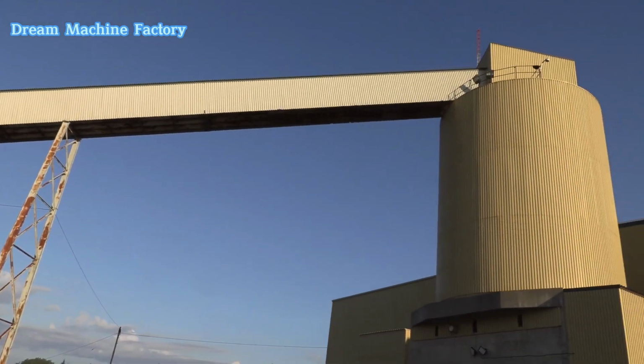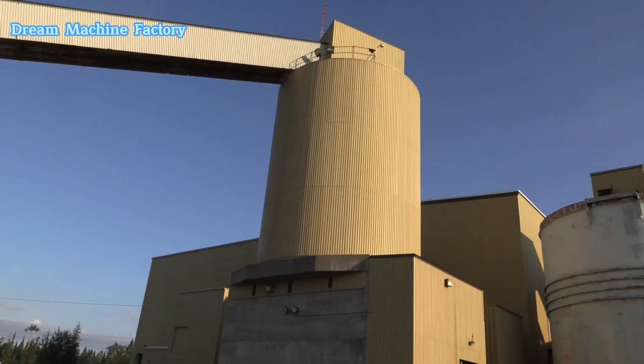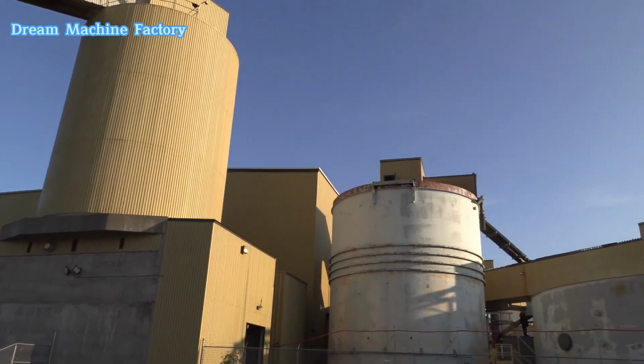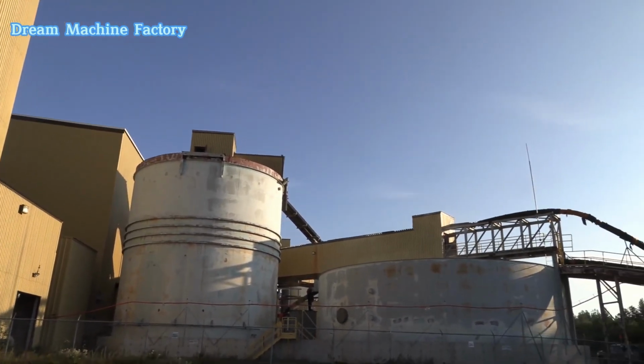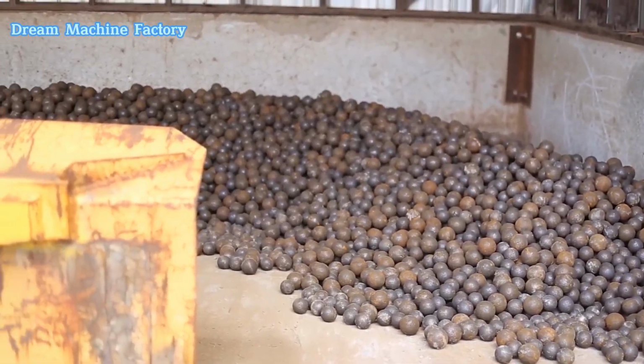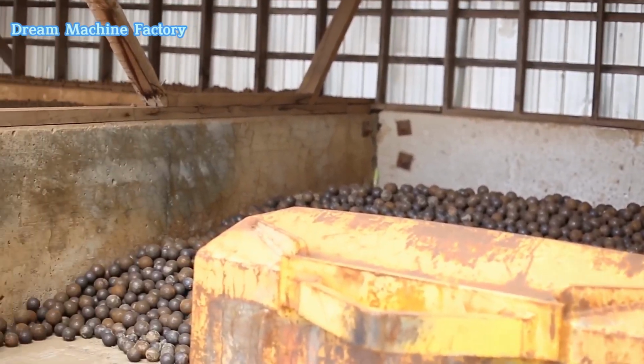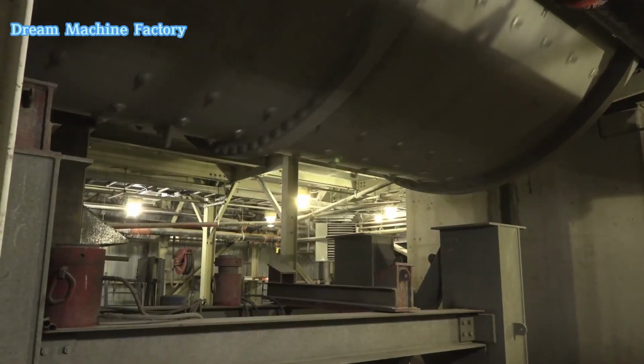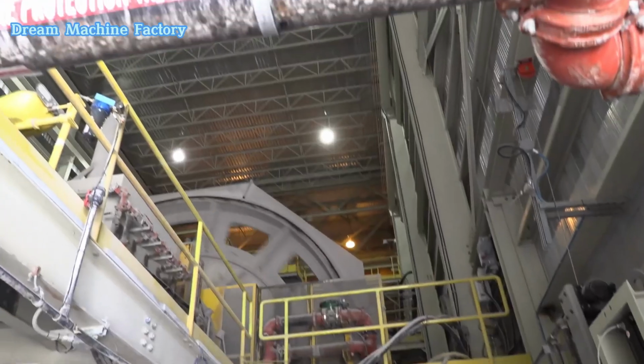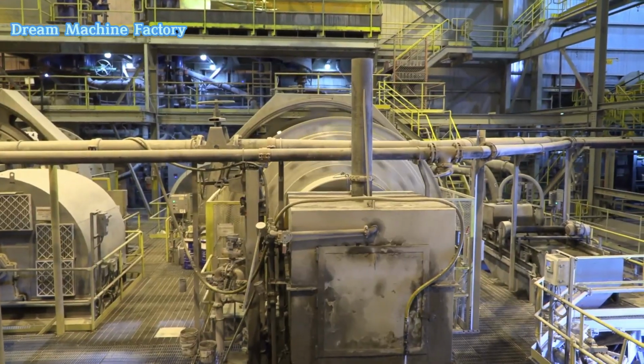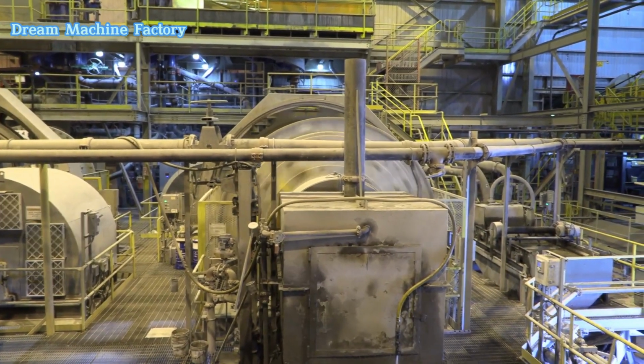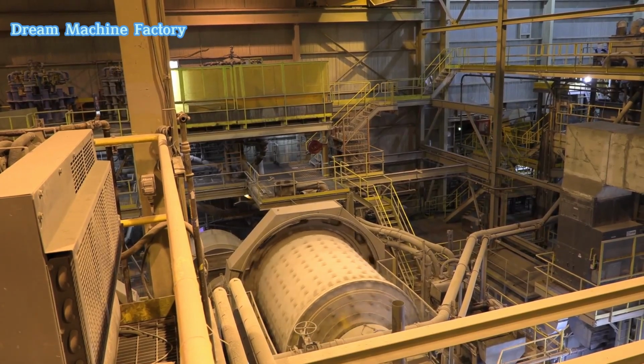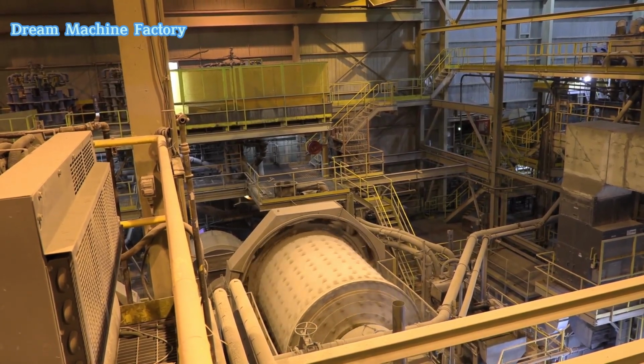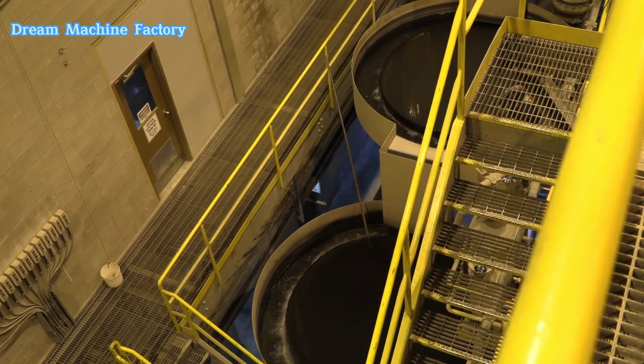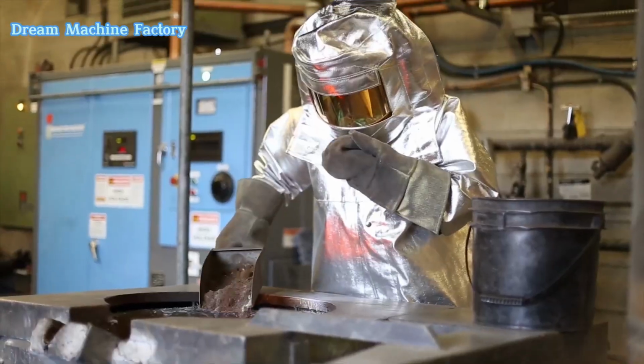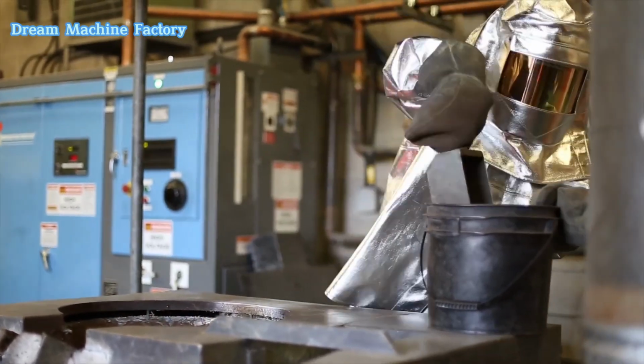From there, the ore is transferred to the fine ore bin, which holds up to 1,600 tons of ore, about the weight of 14 blue whales. The ore is then fed into grinding mills, where it is further broken down by thousands of steel balls, each measuring 2.5 to 3 inches. These balls grind the ore into even smaller particles. Once ground sufficiently, the ore moves to another mill, filled with 1-inch balls that help refine the material into a finer slurry. Next, the ore is introduced to leach tanks, where it is treated with chemicals that extract the gold.